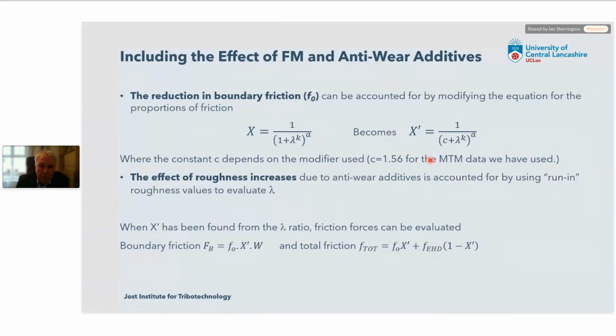By incorporating an extra coefficient here, this parameter C will allow us to deal with the change in the boundary friction coefficient. And in the data that we collected, which I'll show you in a moment, C was about 1.5, 1.6. And we can deal with the change in roughness by measuring the additivated surface roughness and using it in creating this parameter x prime. The rest of the process is exactly the same.